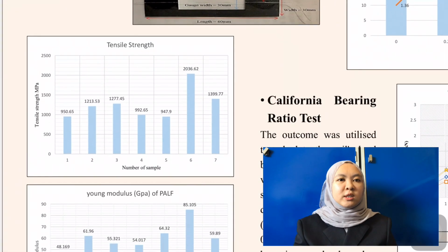Based on the tensile strength graph, the lower value is 947.9 and the higher value is 2036.62 MPa. Singha 2020 mentioned that the tensile strength ranges from 413 to 1627 MN per meter squared. The average tensile strength used in this study is 1259.80 MPa.